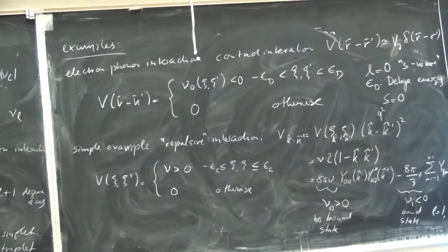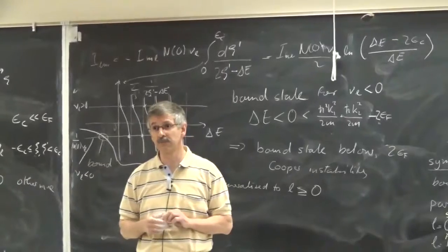There is also the Kohn-Luttinger theorem, which shows you that for a purely repulsive interaction, you can get pairing in higher angular momentum channels. But these have terribly small critical temperatures. So you need some special situations, so spin fluctuations or other types of fluctuations which help you to boost this interaction. By purely repulsive, you mean just a constant positive number for interaction? It could be just simply a Coulomb interaction type of interaction. Just for the pair interaction. Yeah.